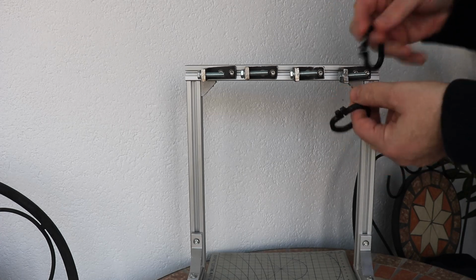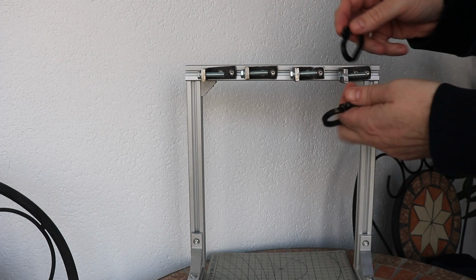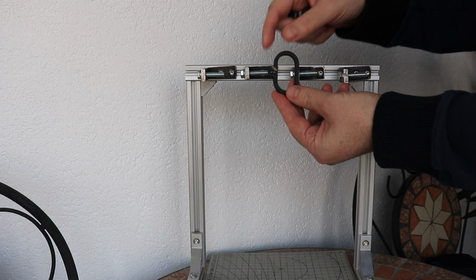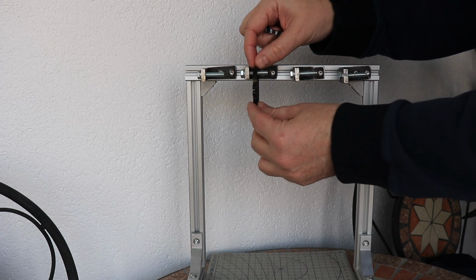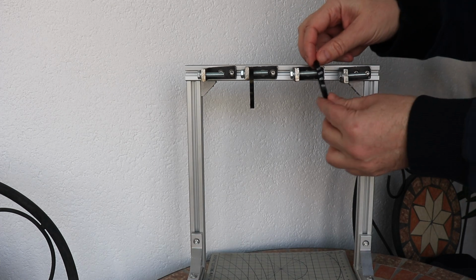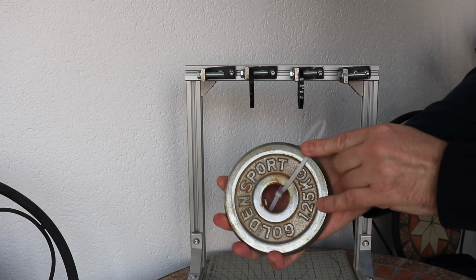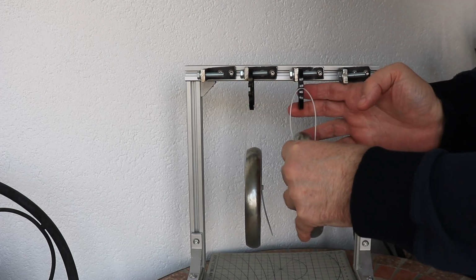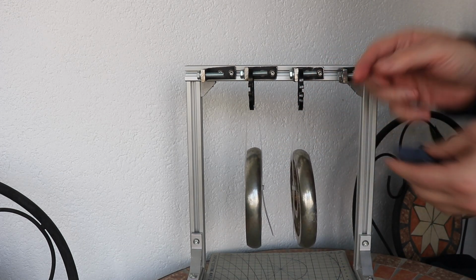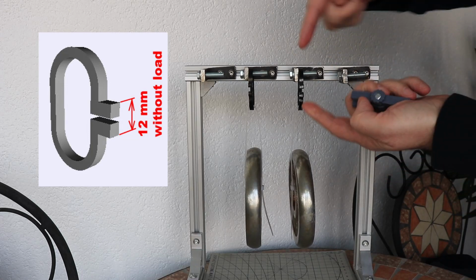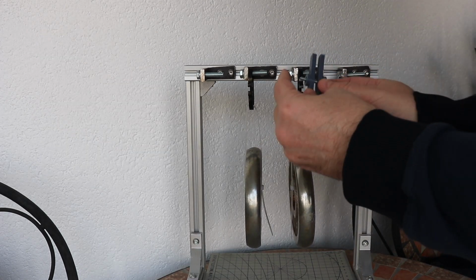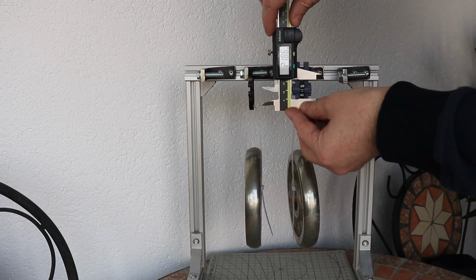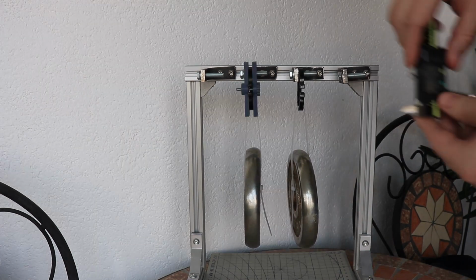The creep test will show us the deformations over time during constant load. So this is the test specimen from the ABS, and this one is from the ASA. 1.25 kilogram load. And now I will lock the position with this holder and measure the distance between these two surfaces. ASA 15.63, ABS Plus 16.18.